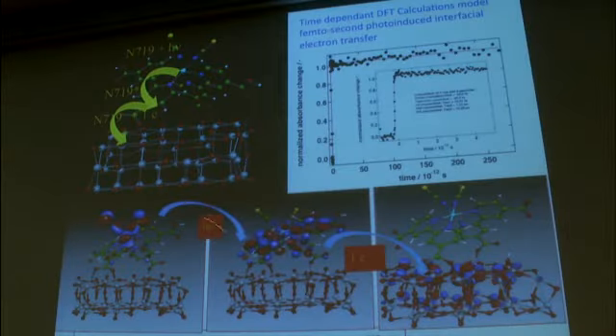So here's the injection. Excitation is shifting electron density from the ruthenium to the ligand, metal to ligand charge transfer. And then we have the injection into the 3d orbitals of the titanium, TiO2. Here we have a kinetic trace. In femtosecond experiments, we see the rise of the oxidized dye signal.